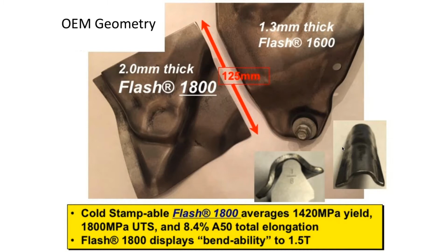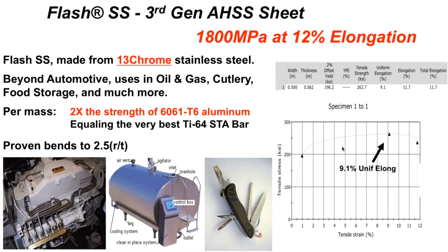Taking it a step further, because people are always concerned about corrosion, we've actually made a third gen stainless steel at 1800 megapascals, but very interestingly at 12% elongation. We used 13 chrome, which is an inexpensive stainless, if there is such a thing. It's 13 chrome, no basic nickel added. And there's a lot of uses beyond automotive.